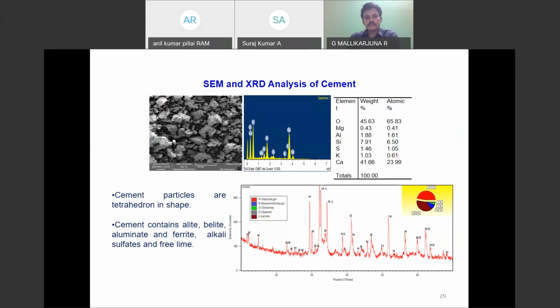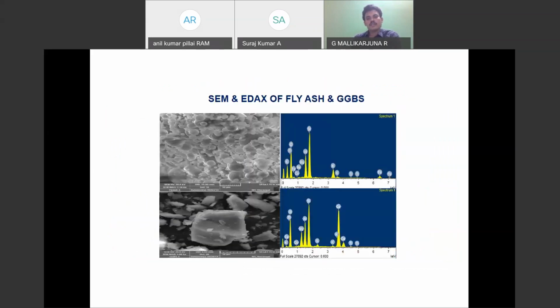And here, if you see the cement XRD analysis we had conducted in our laboratory, the cement particles are of tetrahedron shape. And coming to this, we had the different source materials like alite, belite, and we had identified this with cement XRD analysis. And the same we have conducted for this fly ash and GGBS.